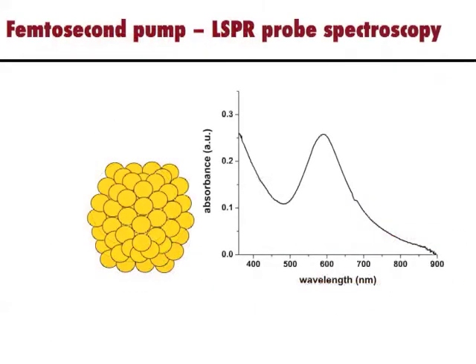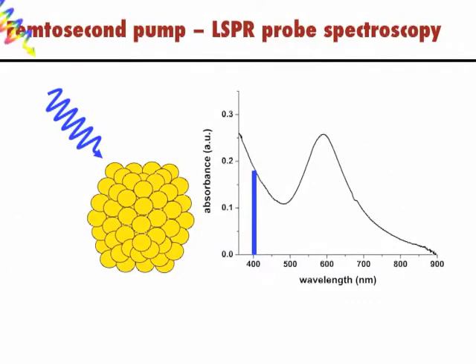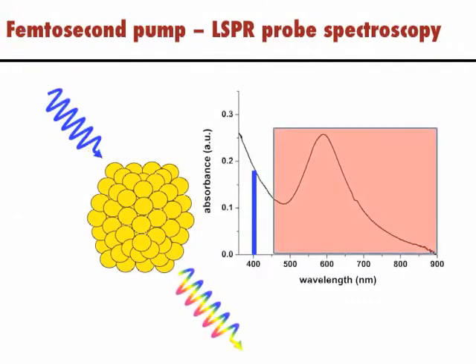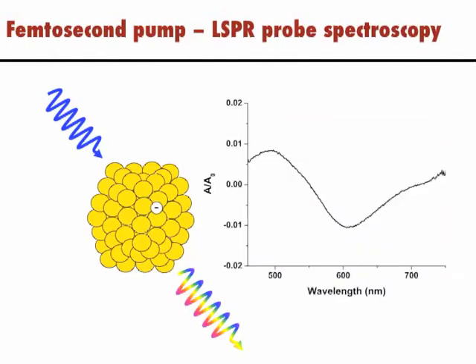Nanoparticle sensitivity can be tested in a controlled manner using femtosecond time-resolved plasmon resonance spectroscopy. Here, a femtosecond laser is used to electronically excite the nanoparticle while the LSPR is monitored as a function of time. The initial excitation generates hot electrons, forming a transient bleach, or negative amplitude signal, at the plasmon resonance. By monitoring the recovery of this bleach in the time domain, electronic relaxation can be studied.